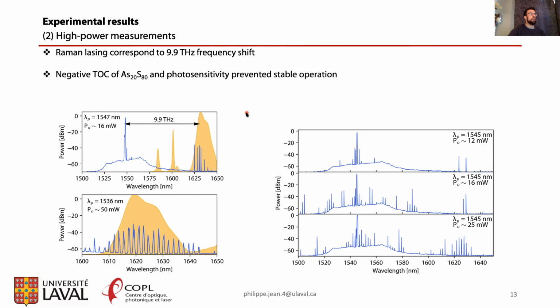So what we did is we actually periodically swept the resonance with a pump laser. And what you can see is Raman lasing that was observed in almost all the resonances we tested at different power. And the Raman lasing wavelength actually fits pretty well with the theoretical Raman shift. And on the right, you can see a single resonance that was pumped at different power. And in addition to the Raman laser lines, you can actually see frequency conversion that is attributed to parametric oscillation.